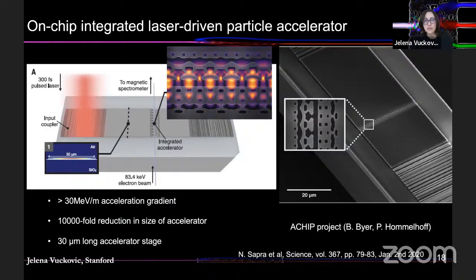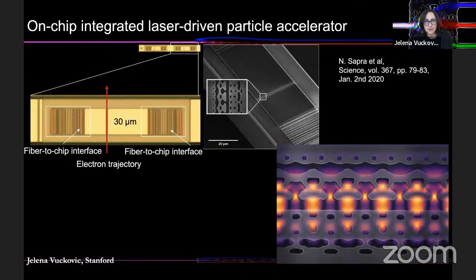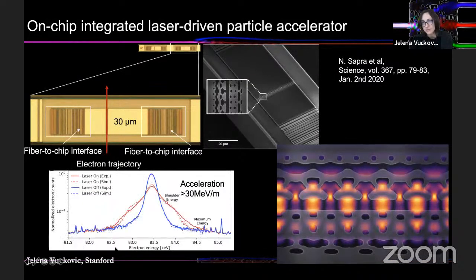And we were able to demonstrate 30 mega electron volts per meter acceleration gradient, which is already on par with some already useful accelerators. So let me show you the experiment. Again, repeating just the structures that I showed you. When the laser is off, then electrons enter and exit the structure with the same energy. That's the blue curve, but then when the laser is on, you see electrons getting accelerated by about 1 kilo electron volt within this 30 micrometer length, which is converted to 30 mega electron volts per meter acceleration. And keep in mind that this is just a single stage of the accelerator.